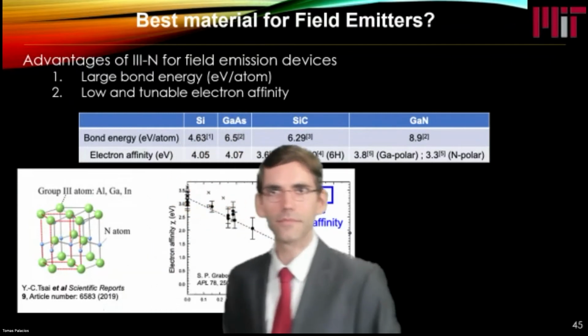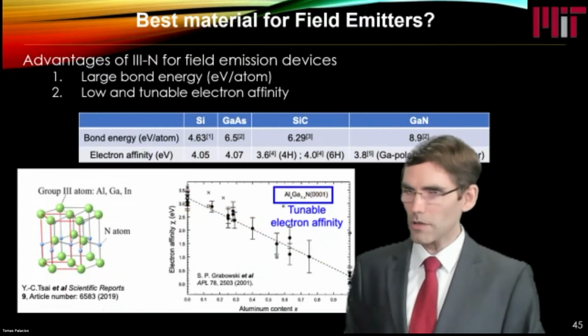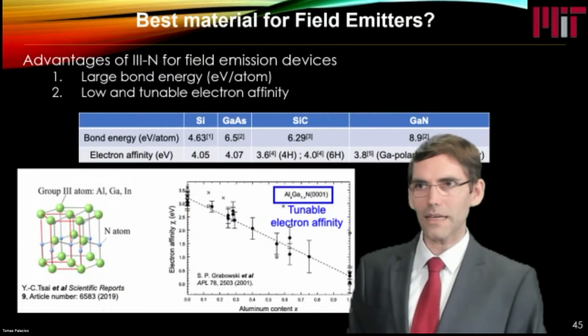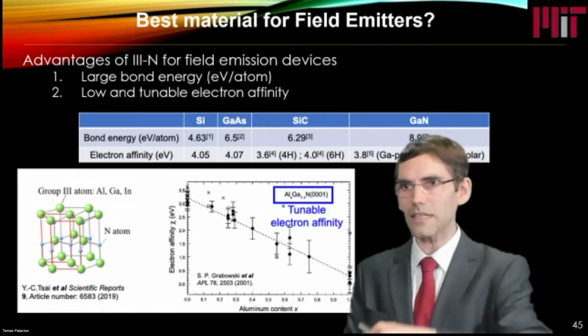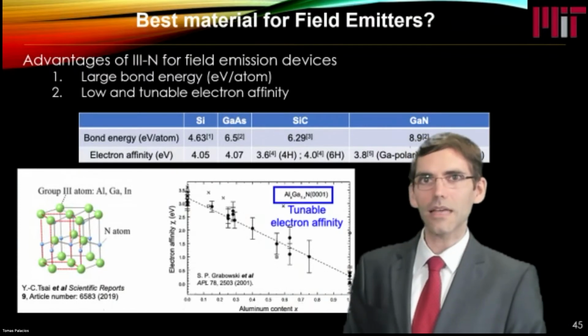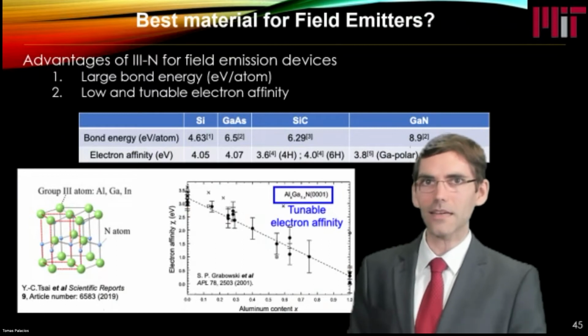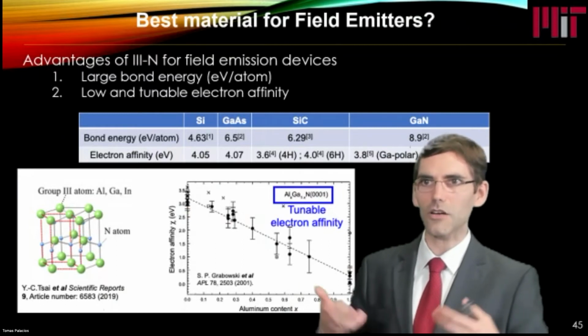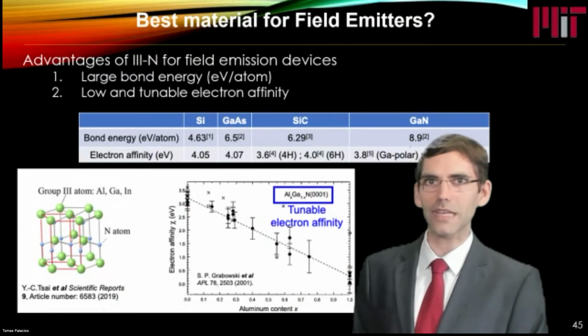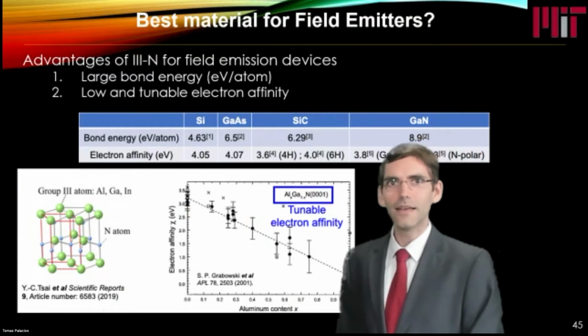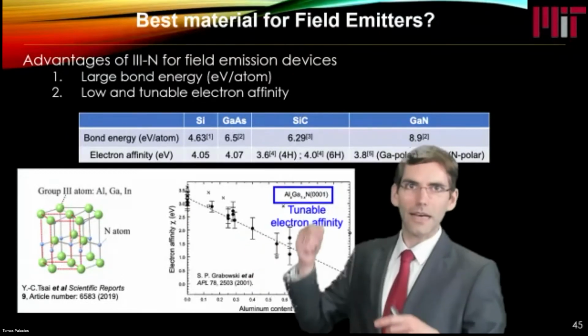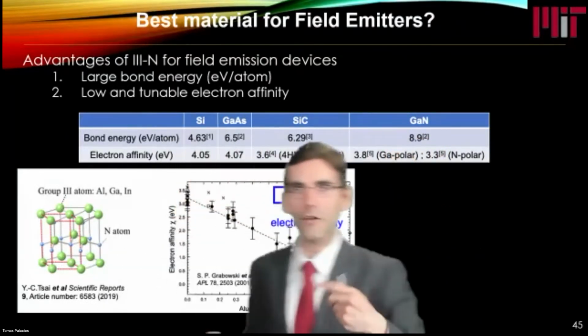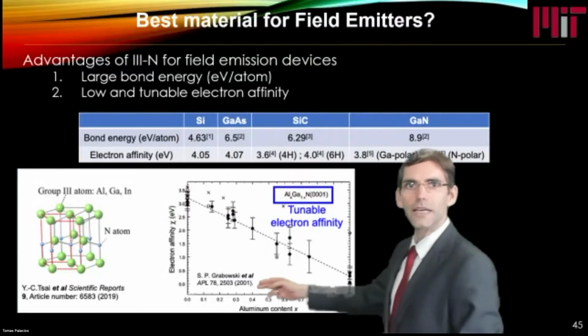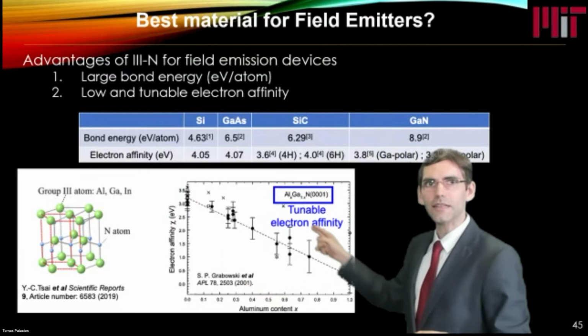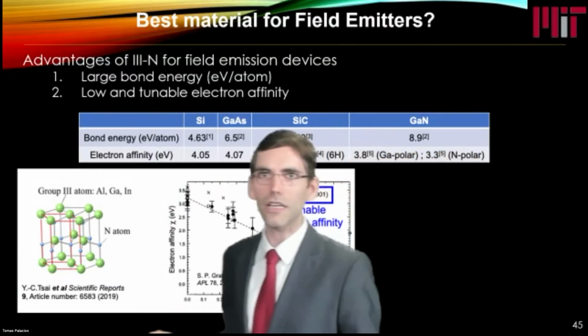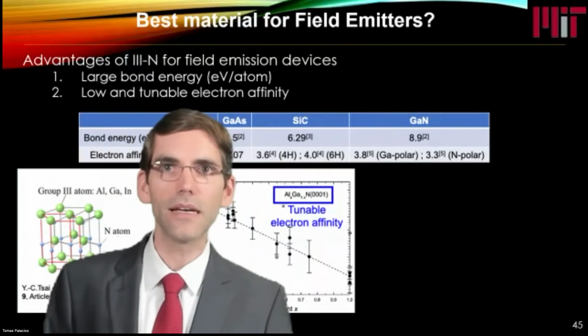What's the electron affinity of gold? Of gold, I don't remember. Typically metals have lower electron affinity. It's easier to remove carriers, but the challenge there is that gating is a lot more difficult. How to turn off the device is a lot more difficult with metals. But actually, gallium nitride is good, but aluminum nitride is better. By adding aluminum, you can bring the electron affinity down to 0 or even negative values. So I think this is quite promising.